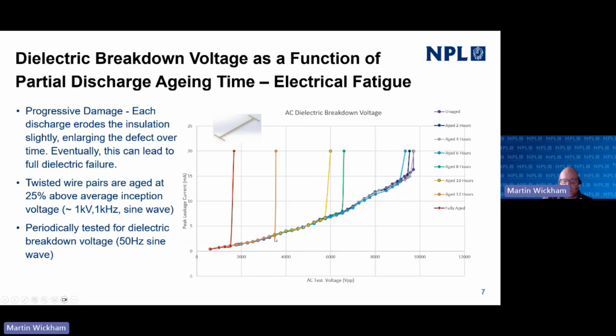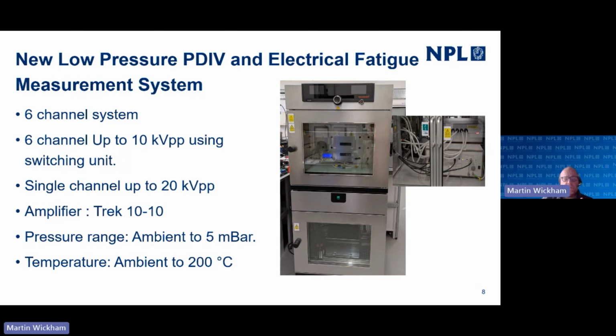You increase aging for longer until you get down to the point where, in this case, we're below 2000 volts after 12 hours plus of aging. Obviously, the aging time depends on the voltage. It depends on the waveform. It depends on the pressure. But effectively, all of this is happening, and you're lowering the dielectric withstanding voltage until you're down to the voltage that you're operating at, in which case you get a full electric discharge at that time. So this is what our system is designed to look at.